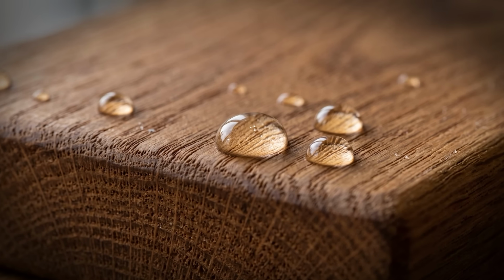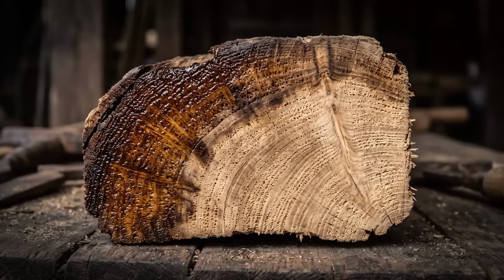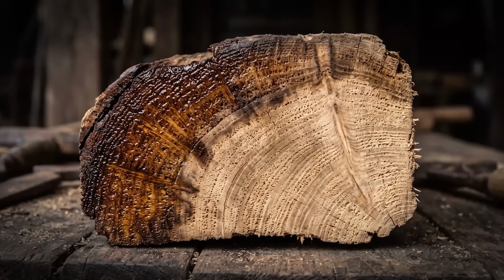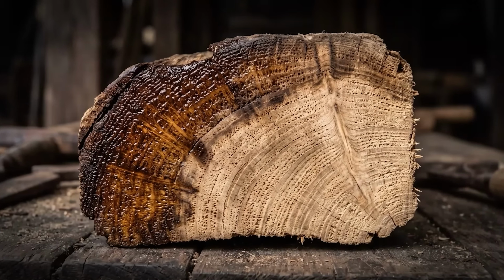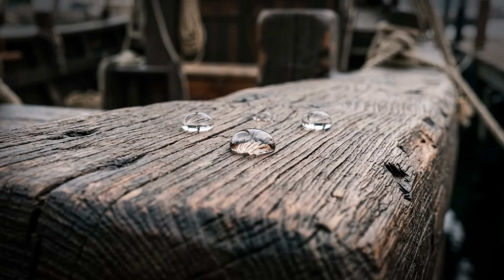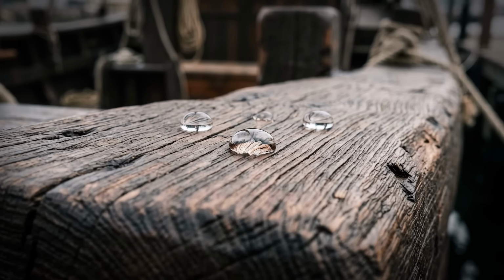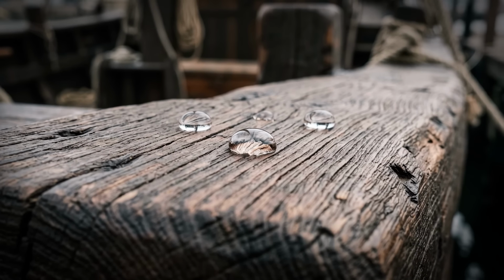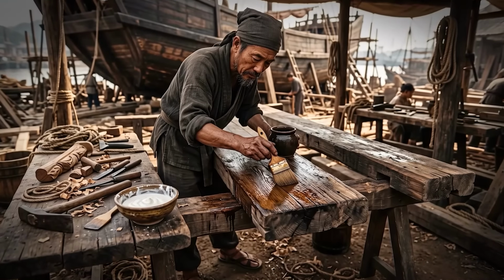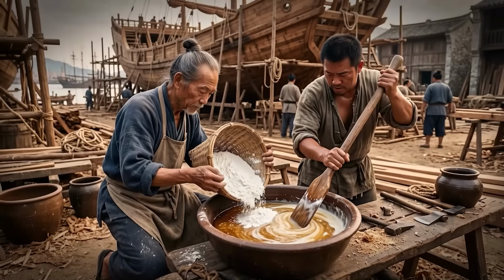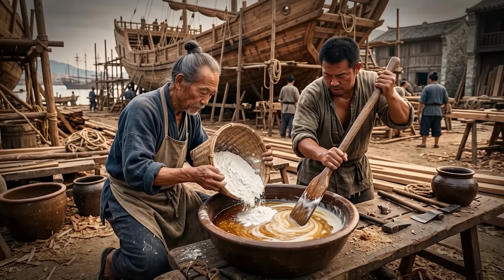Tung oil has a low enough molecular weight that it penetrates deep into the porous cellular structure of the timber before the polymerization process completes. It does not coat the wood, it becomes the wood. The outer layer of the timber itself is transformed into a hydrophobic, structurally reinforced barrier. There is no interface to fail. There is no film to peel. But the oil alone was not the breakthrough. The breakthrough was what happened when it met the burned shells.